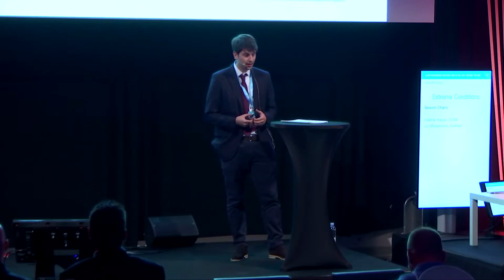Achieving a design with a blast-resilient glazed facade is a complicated problem. Typical monolithic glazing products, such as annealed, heat-strengthened, and toughened glass, are brittle and have no reserve capacity beyond fracture. In addition, many glass-related injuries have been observed in blast events due to the projection of glass shards at high velocity. Therefore, laminated glass panels that fail in a more ductile manner and can reduce glass-related injuries as glass fragments remain attached to the interlayer are often preferred for blast applications.